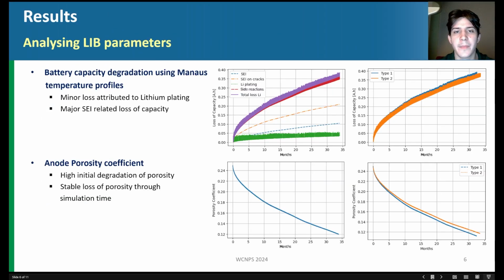First, regarding capacity degradation. Under Manaus temperature profiles, we observed that lithium plating contributed only for minor losses, while the SEI growth was the main driver of capacity fade. The total loss of capacity at the end of the real temperature scenario was around 0.37 amp-hours. In the projected scenarios with the type 1 temperature profile, the hottest one, it reached 0.40 amp-hours at the end, while with type 2, the loss of capacity was around 0.39.